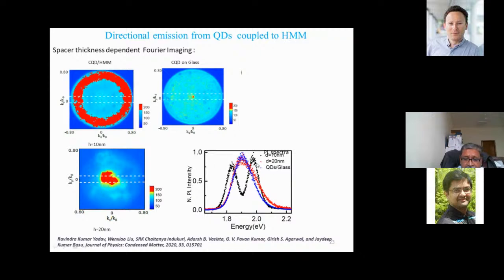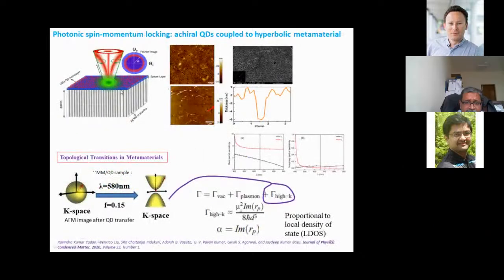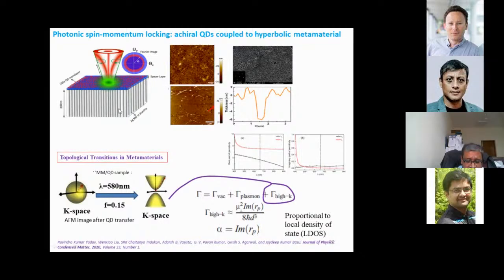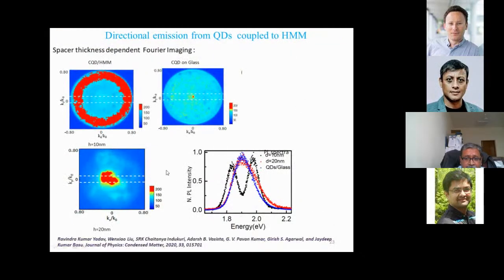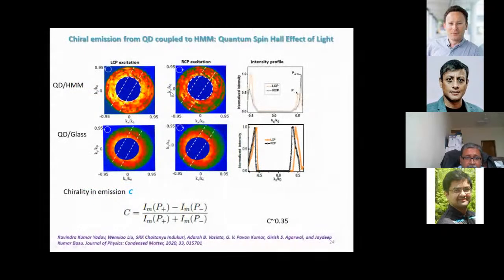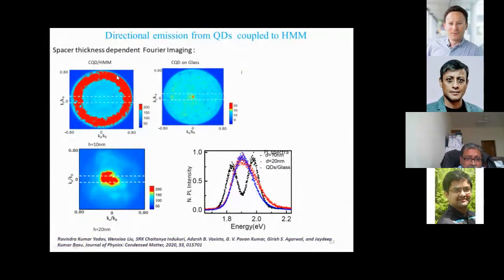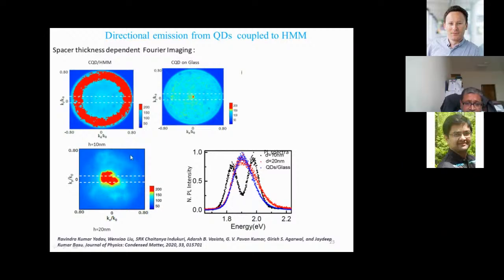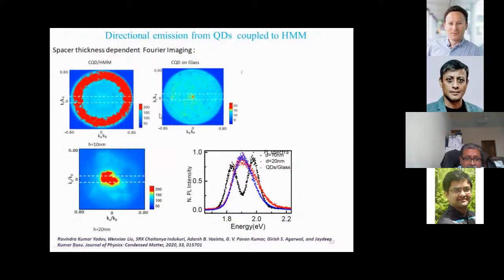And it also depends on the thickness, which is interesting. That means how thick the spacer layer in between is, as indicated here, and the thickness will tune how well these quantum dots are coupled to these evanescent modes. These modes are evanescent, so you want to couple them. Otherwise, you can't access them from outside. So the spacer will determine how well you are able to couple to this evanescent mode. This is one thing which emerges, and it is coming purely because of this template. The directionality comes from that.